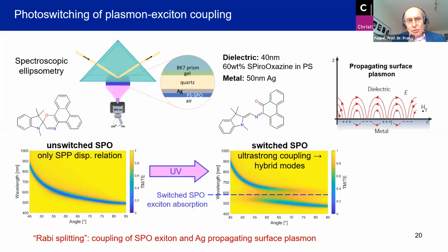What we are interested in is to switch the resonance frequency of the propagating surface plasmon by using photoswitchable molecules, and by coupling the exciton process in these chromophores, which is reversible and can be photoswitched, with the plasmon resonance. Here, the basic idea is what you know from textbooks. If you have harmonic oscillators, say two spring pendula which have the same resonance frequency, and then you increase the coupling between the spring pendula, at a certain coupling strength you go into the regime of the so-called strong coupling, and then instead of observing the resonance frequency of the oscillators, you get a splitting.